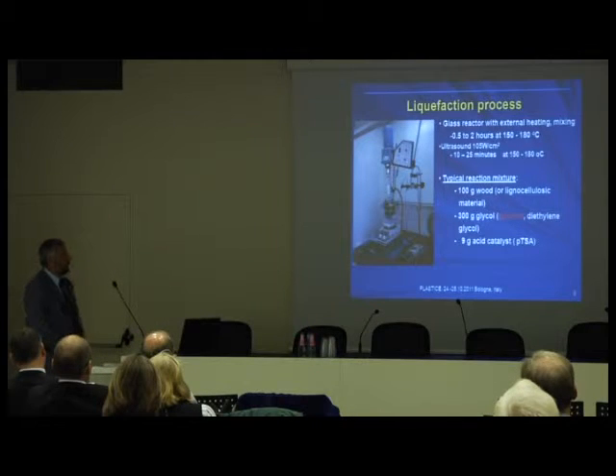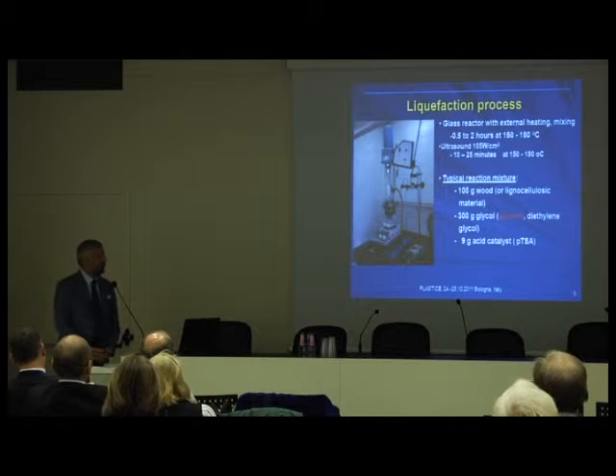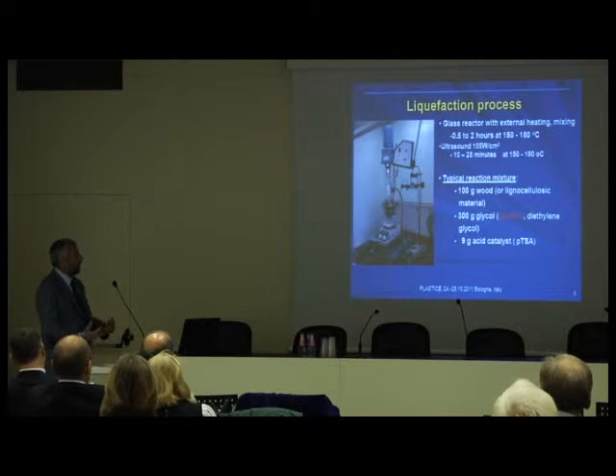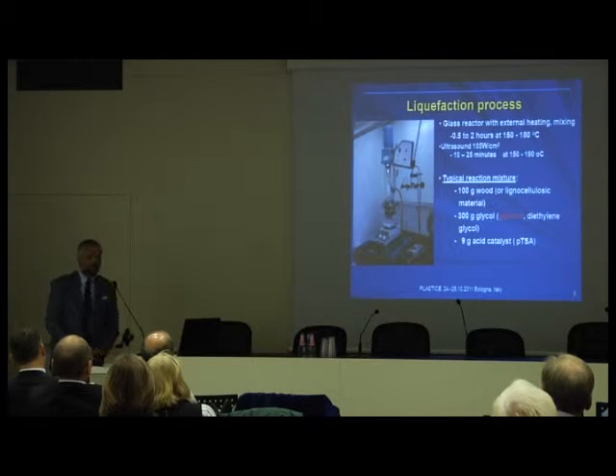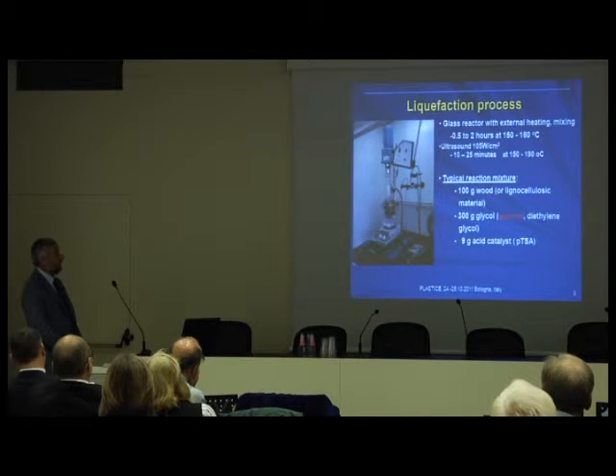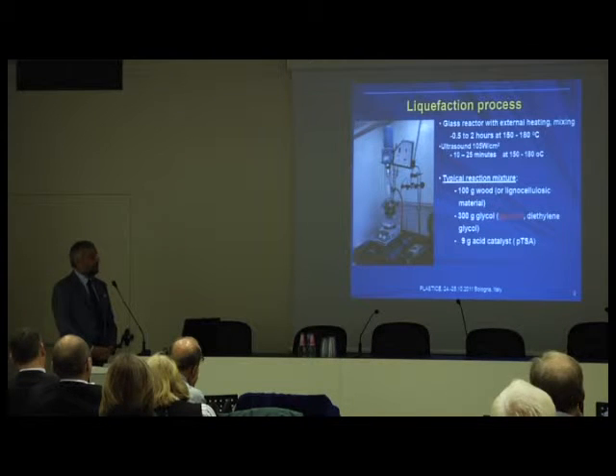You can see here on this slide how it looks in our lab. It is a simple glass reactor heated up to, let's say, about 180 degrees. The classic process lasts about 2 hours, but our invention is to use ultrasound to increase the speed of the reaction. And instead of 2 hours, we finish the liquefaction in 20 minutes. So it means that this input with the ultrasound is very effective for this process.